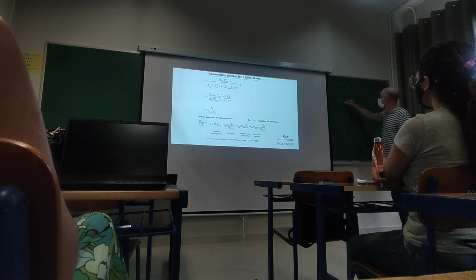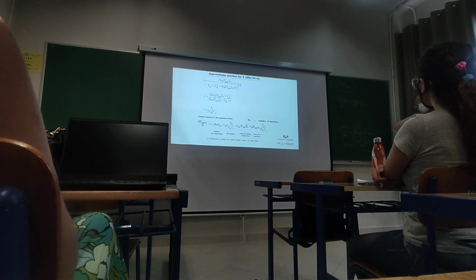So you will have these radicals formed because the initiator is decomposed in the aqueous phase. Also, radicals exit from the particles to the aqueous phase, given by the concentration of radicals in the particles multiplied by the Avogadro's number and the volume of the phase. So these are the two positive terms.